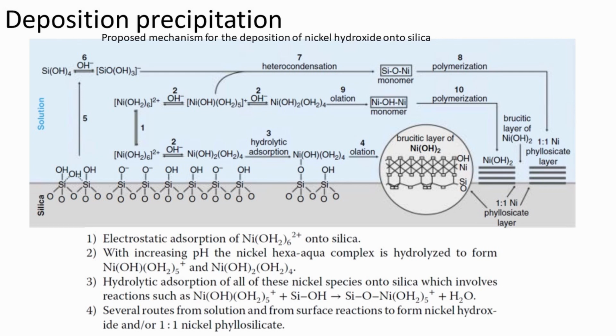The mechanism of deposition precipitation can be explained at a molecular level as shown on the figure on the slide. At the beginning of the basification of the solution, silica is negatively charged and exhibits cation adsorption capacity because the pH is higher than its point of zero charge. For silica, the point of zero charge is equal to 2. And the first step of deposition precipitation is probably an electrostatic adsorption of the nickel hexa-aqua complexes on the silica surface.